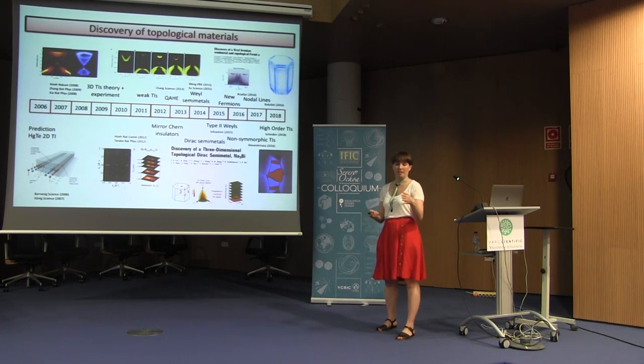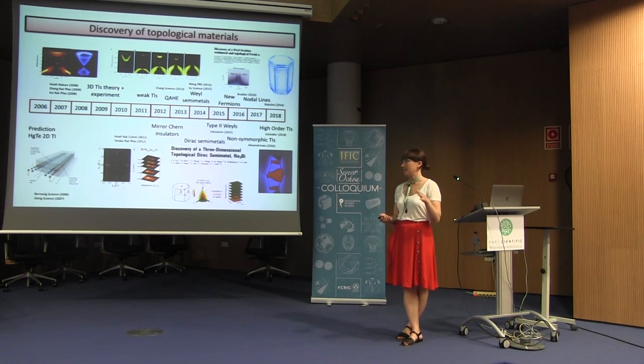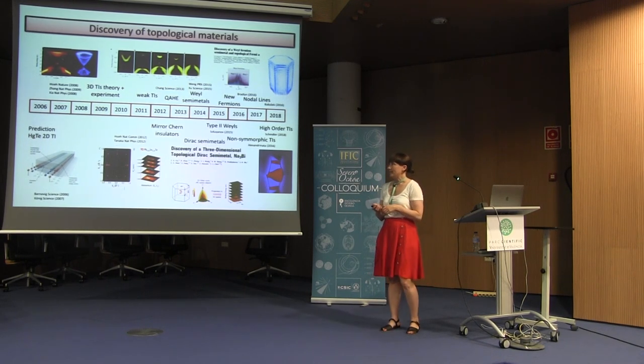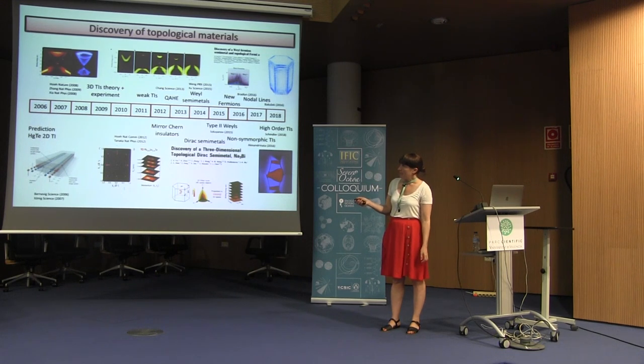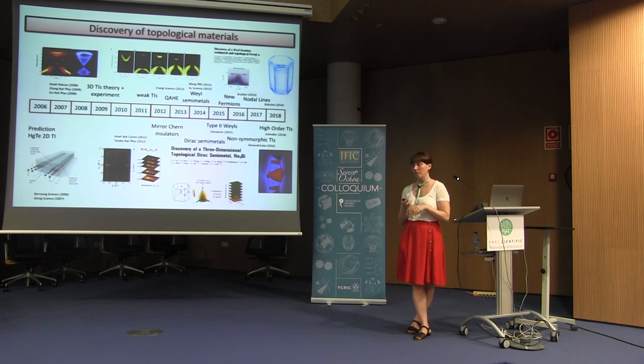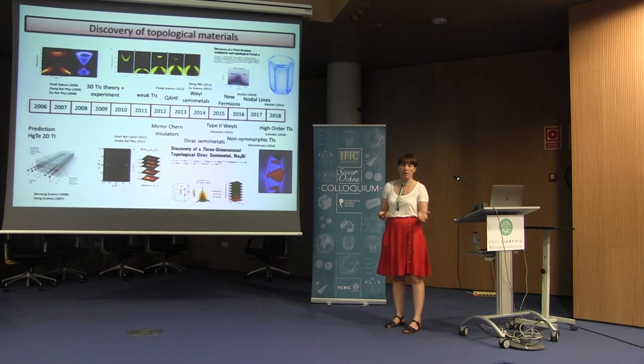This means that the edge state could not disappear unless we break that symmetry, and that can only happen with a magnetic field or magnetic atom. In 2011, for the first time, a new symmetry protecting these phases was introduced, and it was mirror symmetry. They were called topological crystalline insulators. We could have this edge state in some particular surfaces perpendicular to this mirror, and they were protected by this symmetry, which means that to break the conducting properties, one has to break the mirror symmetry.